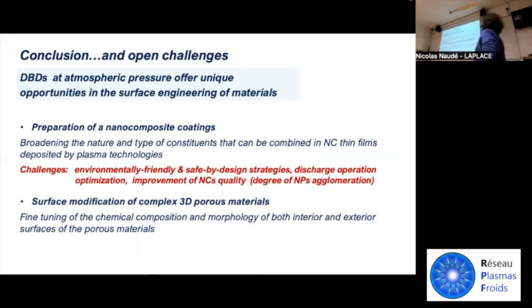As far as the preparation of nanocomposite coatings is concerned, we can conclude that this approach can help us to broaden the nature and type of constituents that could be combined in a nanocomposite thin film deposited by a plasma process. However, we have several challenges to face, and here, for instance, in Toulouse, I perfectly know that there are very, very interesting results on the possibility of using environmentally friendly and safe-by-design strategies. It's very important to also improve the discharge optimization and improve the nanoparticle quality, the nanocomposite quality in terms of agglomeration. And this is really flexible, so it depends on the application.